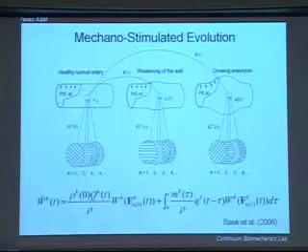So here's really the main slide. What we show here is an academic growth of an aneurysm, so we're going to keep it simple, that is axisymmetric. What we've done is we've endowed this wall with various properties, that is elastin, various families of collagen with the orientations that are measured, and smooth muscle. Then at time 0, we numerically degrade a small amount of the elastin, thought to be, in intracranial aneurysms like AAA, one of the initiating events.